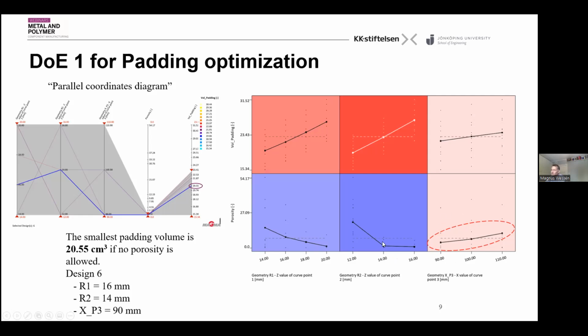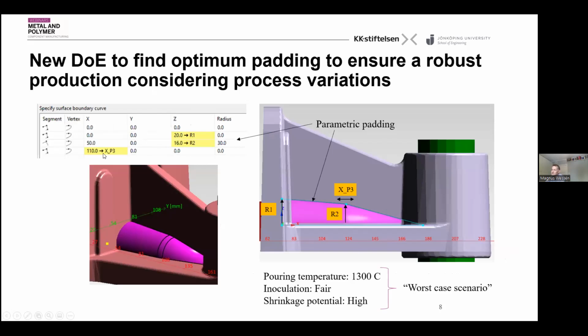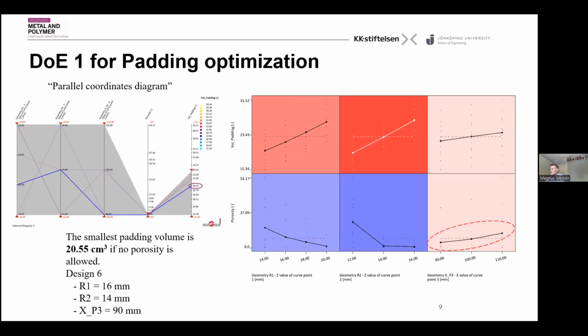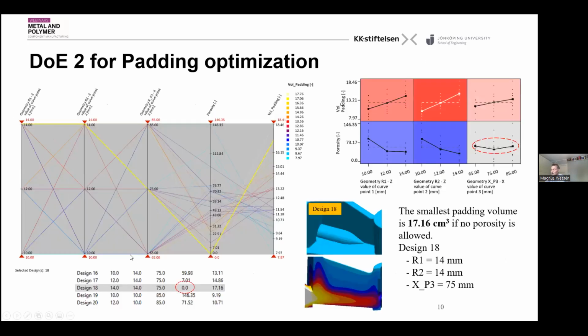Of course, I could have selected a larger design space from the beginning, but that would increase the number of simulations quite significantly. Then it's maybe better to do this in sequence instead. So then, of course, you should try the same things with lower values. I did set up a new one where I went from 10 to 14, slightly lower values, 10 to 12, 14 here, 65 to 85 instead of from 90 to 110. And then we can see that there's one design, actually only one design, at the 75 millimeter location for this point, where I actually had no porosities.